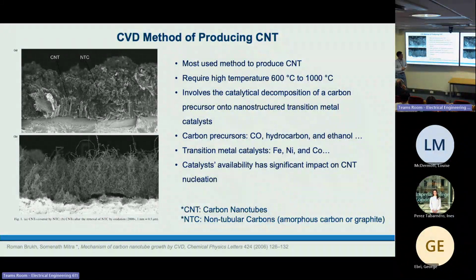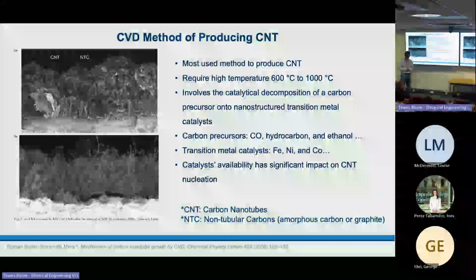The reason why we studied the corrosion of the iron electrode cathode is that because the iron gets oxidized during the heat up process, it forms some small nanoparticles or nanostructures on the surface of the electrodes. In that case, it forms the nucleation site to facilitate the growth of carbon nanotubes. So I think that's the case. That's why, if we switch these two, during the heat up process the iron electrode is already oxidized, while maybe the nickel electrode is not oxidized as desired, so that didn't give the carbon nanotube products. Yeah, that's my hypothesis.